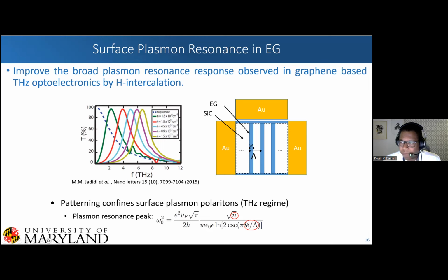And you can control it by actually confining your plasmon resonances by patterning it. And so because all of our quasi-freestanding epitaxial graphene samples are 10 to the 13, we can focus on just patterning to control this, as well as gating. And we can actually control this through gating as well.